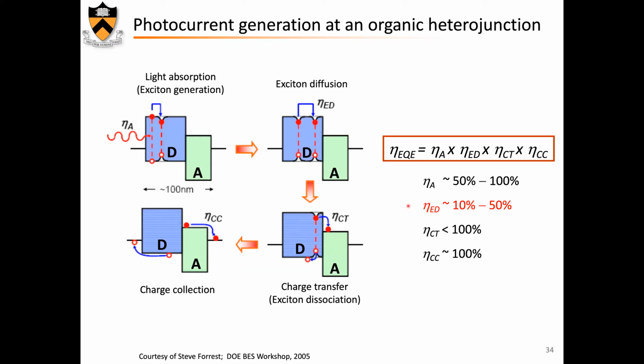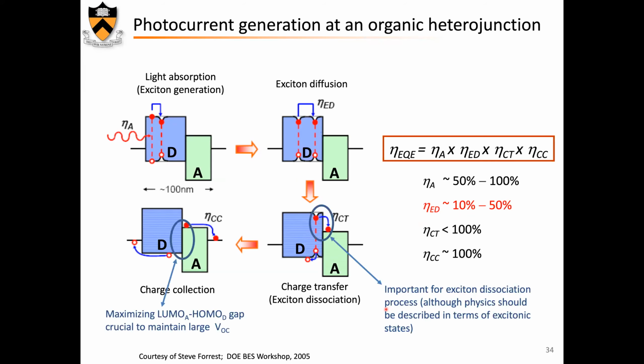The exciton diffusion probability is a big issue, and it's certainly not 100% or so, nor is the dissociation of the electron and the hole once you form this charge transfer exciton. This step here is important, although this is a very simplistic way to look at it, and you should look at the physics of the dissociation of the charge transfer exciton through an excitonic state process. And of course, the energy difference between the LUMO of the acceptor and the HOMO of the donor is also very important, because eventually it limits the open circuit voltage that you can get out of this material.